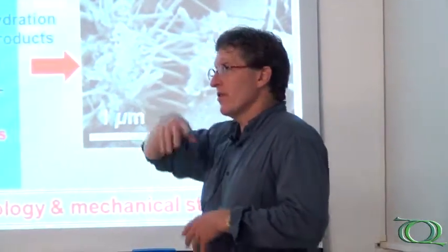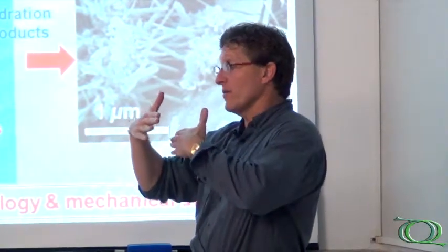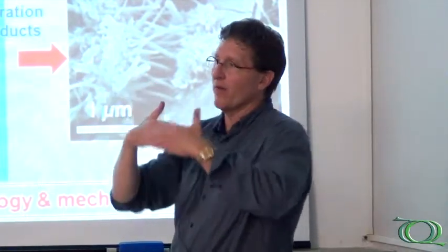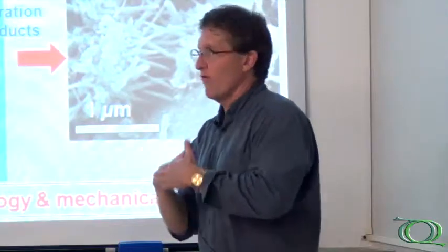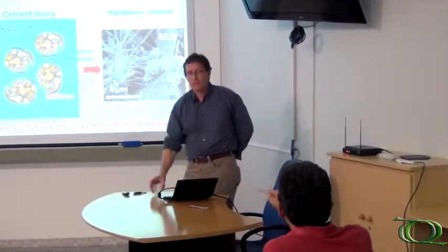Regarding oxygen vacancies, you can have them in zeolites over longer times. If you keep the structures for longer times, you will have oxygen vacancies. Well, I mean, on the surface of all these particles, you have hydroxyl groups, right? I guess, is that an oxygen vacancy? I don't know, but the whole surface is a huge defect. Okay. In the case of these layered silicates, you also have silanols on all of them because they're all OH groups on the surfaces. And those are the ones that would eventually cross-link, in the case of the zeolite, to form these structures. When you run the HETCOR experiment between proton and silicon, you can see several correlations.